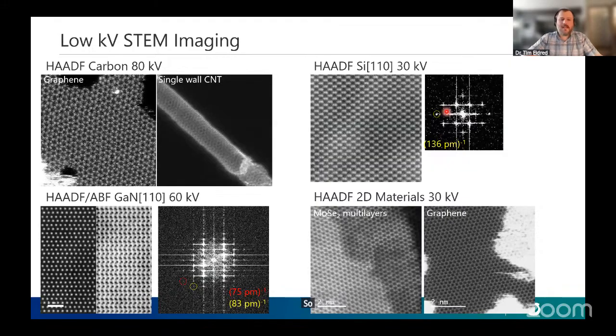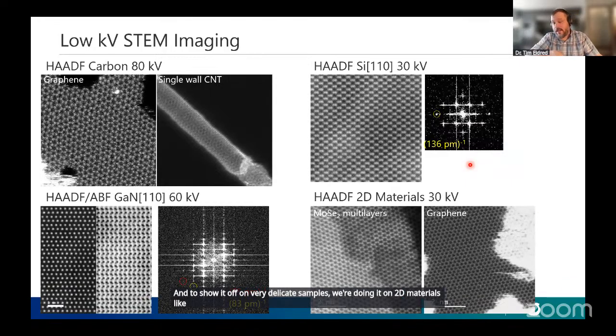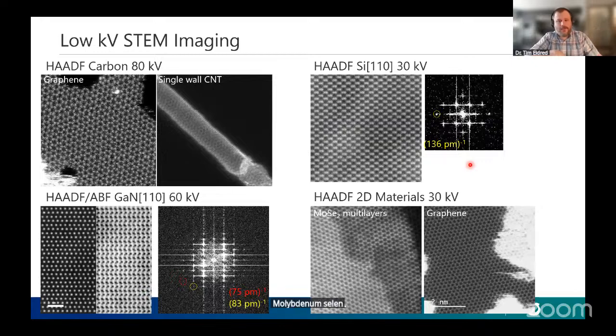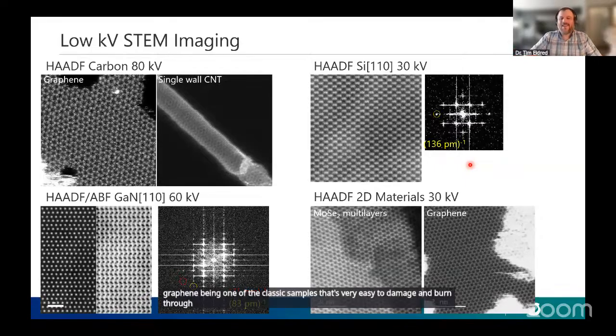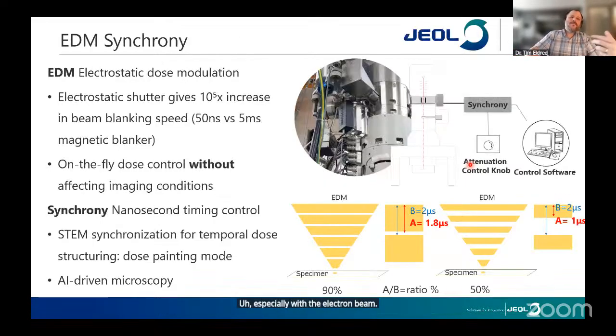So low keV STEM imaging, we're talking about dropping the potential. We've demonstrated high resolution, atomic resolution data down to 30 keV. And to show it off on very delicate samples, we're doing it on 2D materials like molybdenum selenide and graphene. Graphene being one of the classic samples that's very easy to damage and burn through, especially with the electron beam. But when we're talking about dose, what I'm referring to is electrostatic dose modulation.